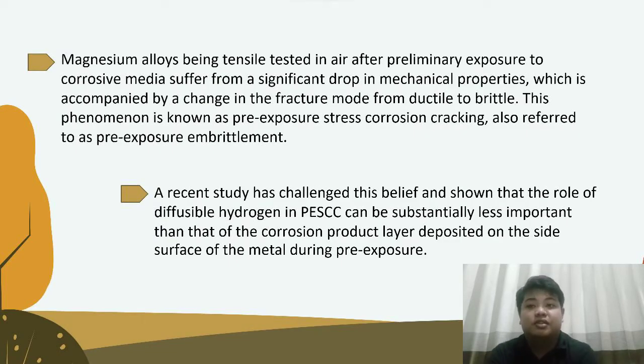Magnesium alloys being tensile tested in air after preliminary exposure to corrosive media suffer from a significant drop in mechanical properties, which is accompanied by a change in the fracture mode from ductile to brittle. This phenomenon is also known as pre-exposure stress corrosion cracking or PESCC, also referred to as pre-exposure embrittlement.